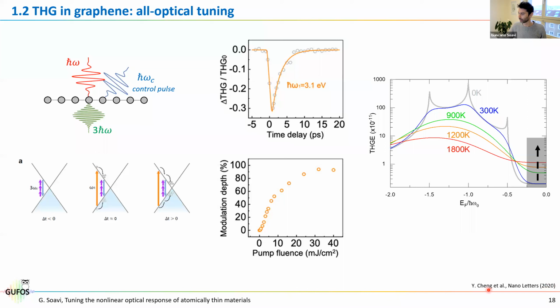Now, this has been done a couple of years ago by this group, this Nano Letters paper. And basically, what they plot here is as a function of the delay between the control pulse and the probe pulse. They see that at negative delays, they have a constant third harmonic. That's quite obvious. Then at zero delay, the efficiency, the third harmonic drops down dramatically, and then it recovers on a time scale that is the typical recombination time of electrons in graphene. You can also look at the modulation depth, and the modulation depth, of course, depends on the fluence, and it grows with the fluence. I mean, they can reach modulation depth up to 90% approximately.